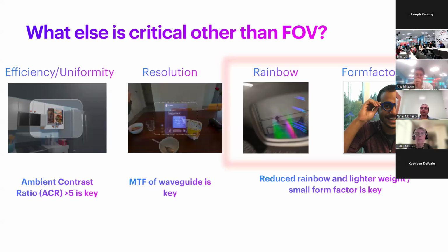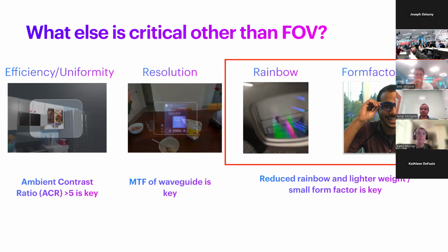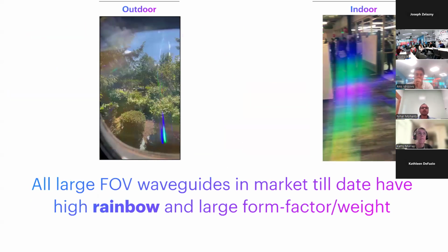This is where all the products in the market have struggled. All it takes for you to be obsessed with rainbow is seeing it once. All large field of view waveguides in the market have high rainbow indoors and outdoors and have a large form factor, with system weight close to half a pound to 2 pounds. For reference, the typical prescription glasses are 15 to 30 grams. The ones that I'm wearing right now are about 31 grams.